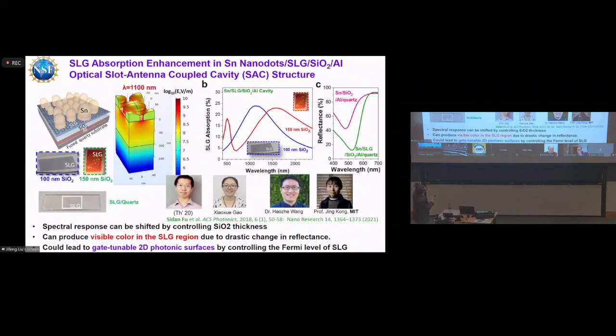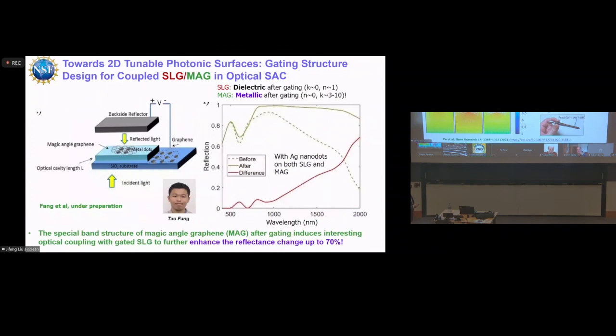This one looks red because, basically, because of the absorption of the graphene, you actually get a strong absorption peak in the green light regime. So that's why the complementary color red is being reflected over here. You can actually get a strong contrast right here. So Tao is currently doing some design,